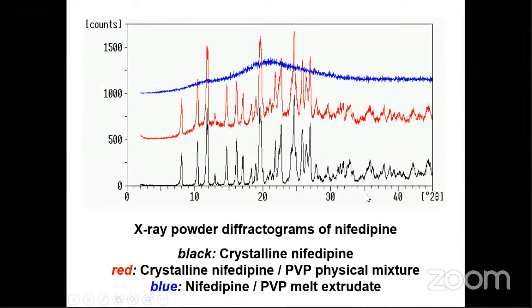After preparation, you have to check whether it is amorphous or not, so again we use X-ray, XRPD. This is the product from nifedipine, black curve - we can see this is a crystalline compound showing very obvious peaks. The red one is a physical mixture of the drug and the PVP excipient, which also shows obvious peaks. The blue one, from hot melt extrusion, is already amorphous. This is how we check it.